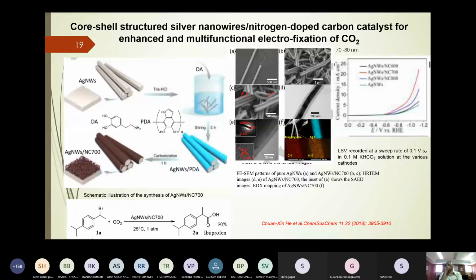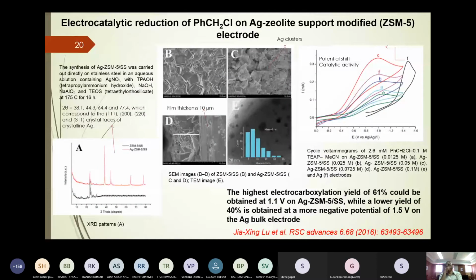Okay. Now, next we go to the formation of a silver zeolite support modified electrode for the conversion of benzyl chloride to phenylacetic acid. See, here I show the method for the formation of silver zeolite support modified electrodes, where we can obtain it from silver nitrate by chemical reduction with TPAOH, tetrapropylammonium hydroxide, plus sodium hydroxide plus sodium aluminate, followed by tetraethyl orthosilicate at high temperature for about 16 hours. There we get the product.